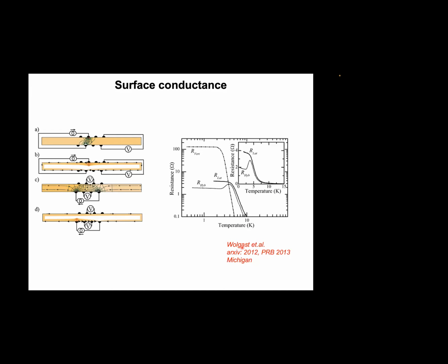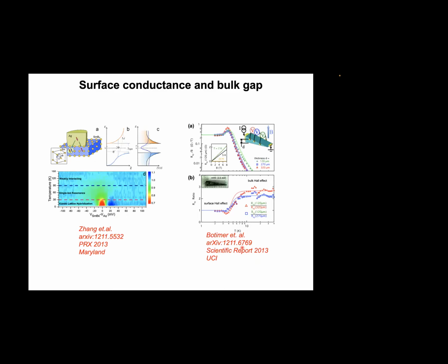I'm also going to say that for this surface conduction check, Jinxia's group from the University of California, Irvine did a similar test, but chose a sample that looks exactly like a wedge. In this way, they tried to measure the electrical Hall signal as you pass the current from one side to the other. Clearly the other geometries stay the same, but the thickness is different. And to the surprise of the community, the Hall voltage does not seem to change with the thickness. I think that also supports surface conduction happening in this compound.